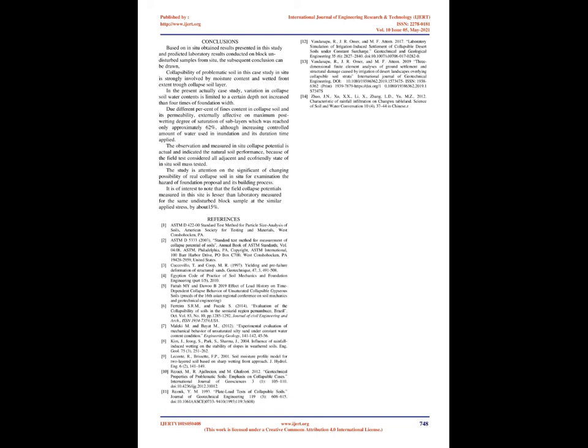The field collapse potential measured in situ is smaller than the laboratory measured, Table 1, for the same undisturbed block sample at the similar applied stress, by about 15%. Conclusions. Based on the in situ results presented in this study and the laboratory results conducted on block undisturbed samples from the site, the following conclusions can be drawn.